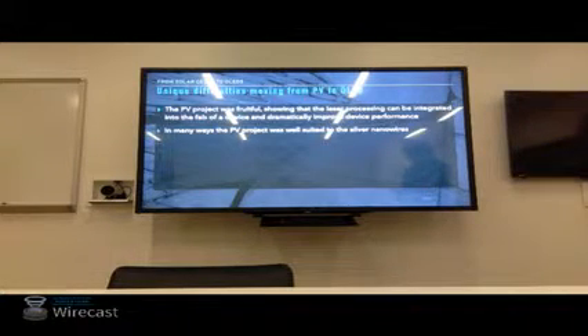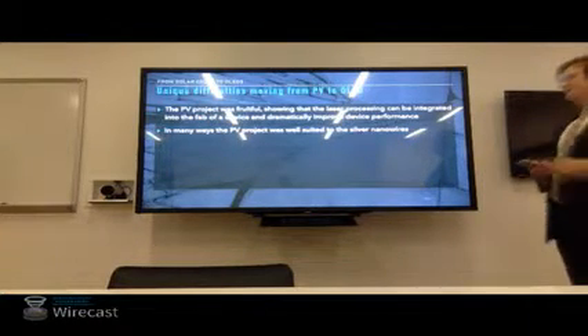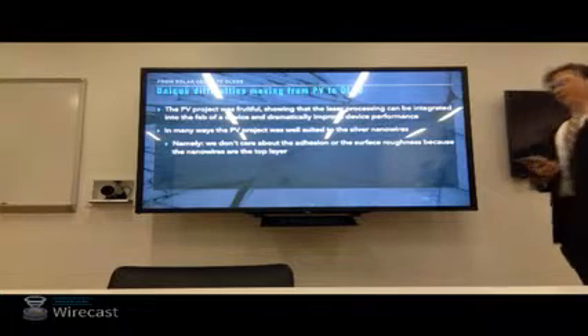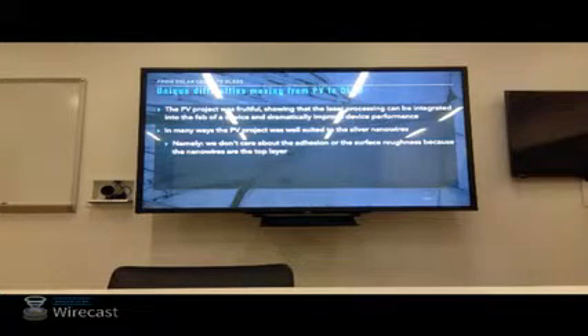But in many ways, it was well suited to using nanowires. If you remember way back to the slide on drawbacks of silver nanowires, we really only had to overcome one here, which was the narrow contact between nanowires. We didn't care about surface roughness. We didn't care about adhesion, and because we had that PVD contact point, we didn't care really about contacting downstream electronics. We kind of heavy-handedly just added a contact.